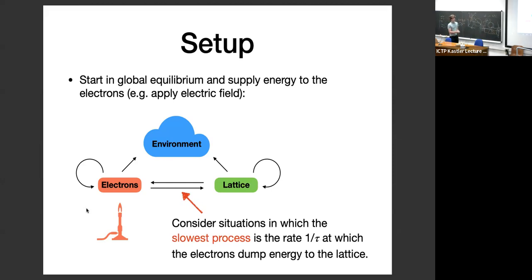So what this is going to buy me is this hierarchy of timescales, which is going to be the theoretical input into what I do. The simplest model of Joule heating is this two temperature model, where the electrons have a temperature, the lattice has a temperature, and they thermalize. In reality, you have to consider more complicated things where they're both thermalizing in parallel. But there's the simplification. A common simplification is one where the electrons and the lattice thermalize separately and then interact.